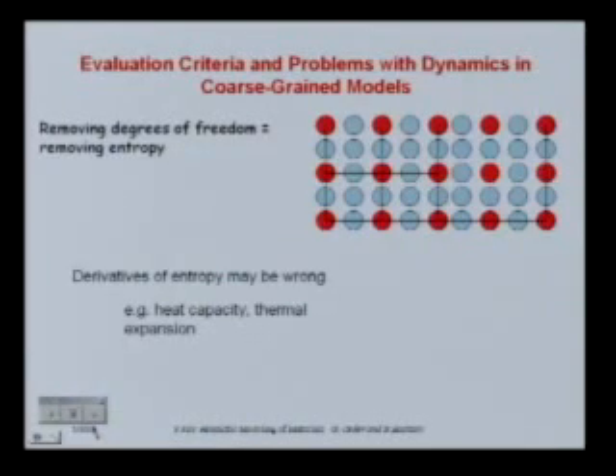The phonon transmission problem is usually recognized very well. There's one that's not as well recognized, but is probably in the long term just as severe: anytime you remove degrees of freedom, you remove entropy. Because entropy is essentially a count of your degrees of freedom.